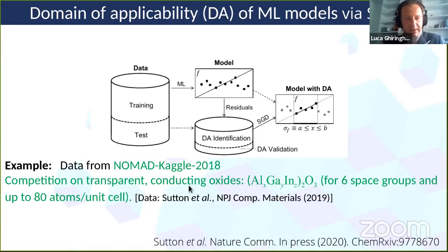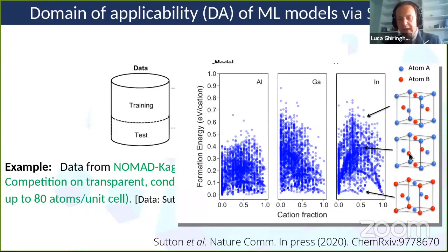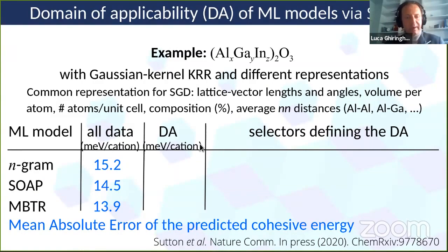What we used here was the data that were used a couple of years ago for the so-called Kaggle competition. That was a hugely successful competition in machine learning for materials science, where almost 1,000 groups competed to make the best model for this kind of materials, for which we gave a few thousand data points. The idea was that you can decorate supercells in different ways with aluminium, gallium, and indium, and you have different formation energies, band gaps, and so on.